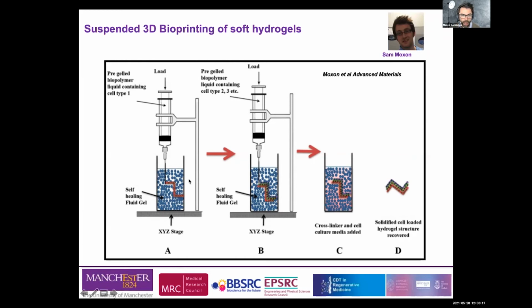How can we achieve this? So we have normally a bath containing agarose, which is a fluid gel, and this bath works as a supporting system, where we can then print inside different bioinks without any cross-linking. And after the positioning of these bioinks, we can then cross-link using ionic cross-linking or UV cross-linking, depending on the materials that we are using. We can culture them inside this suspended bath, or if we need to do any further analysis, we can just wash away the agarose and obtain our three-dimensional construct. So this system actually allows us to overcome the limitations in terms of the printing of low viscosity materials with very high shape fidelity.